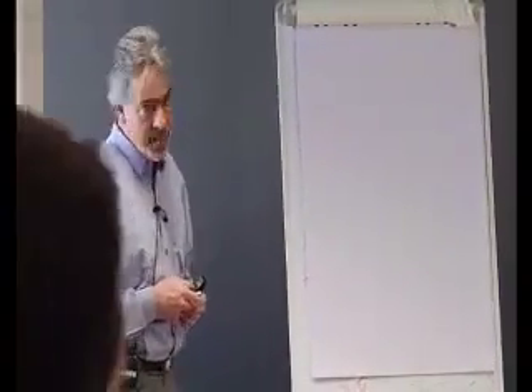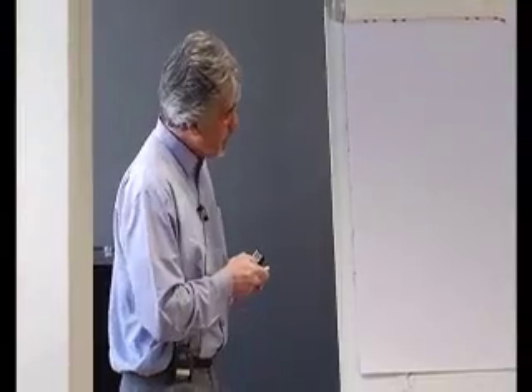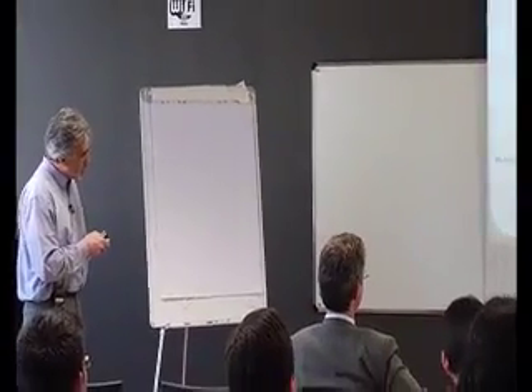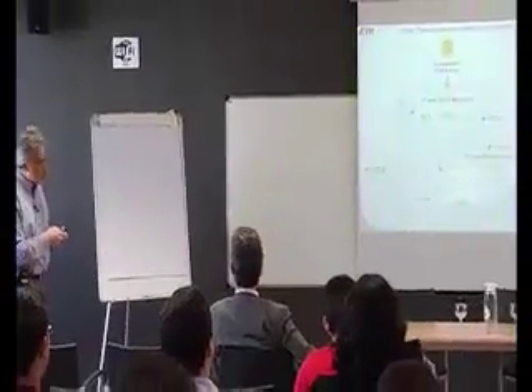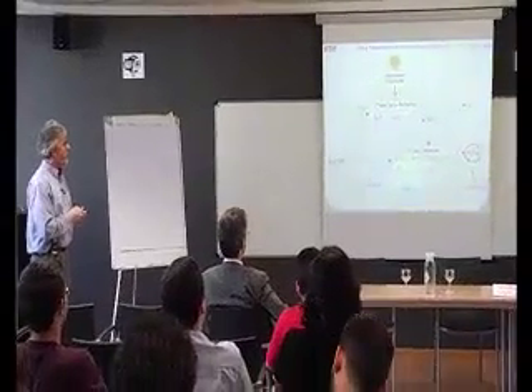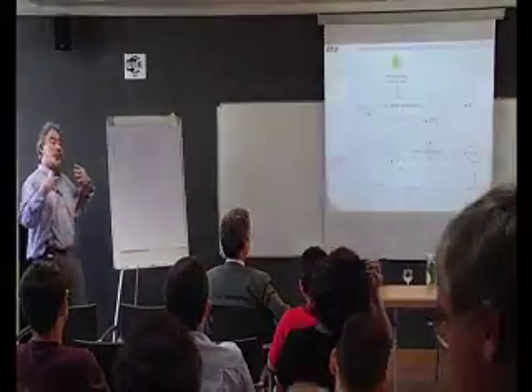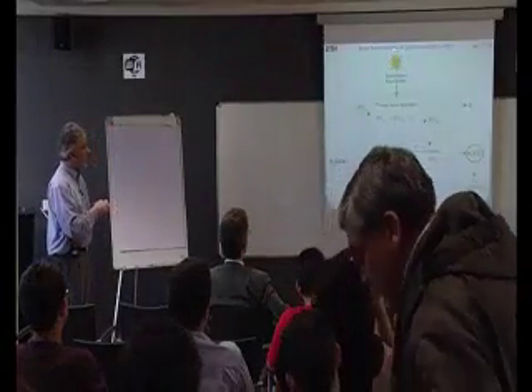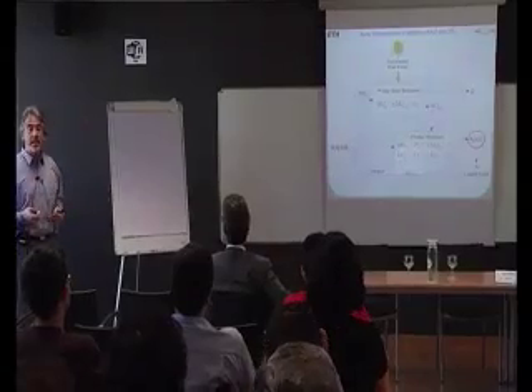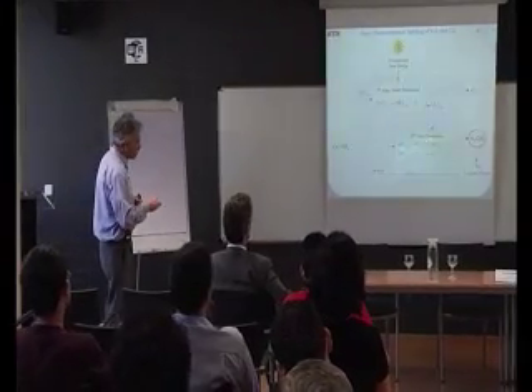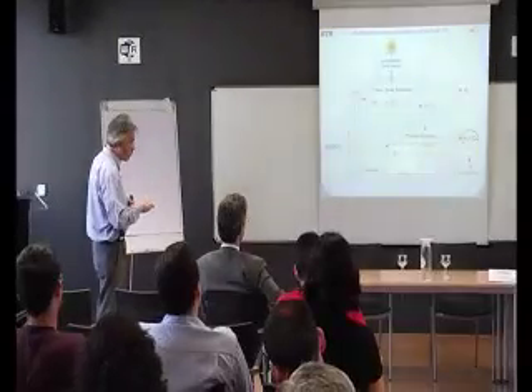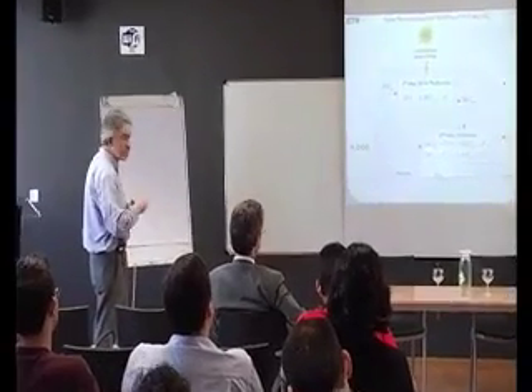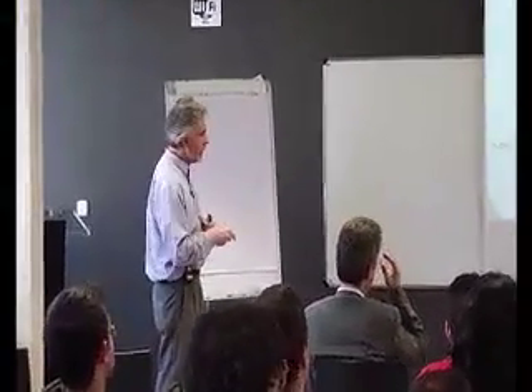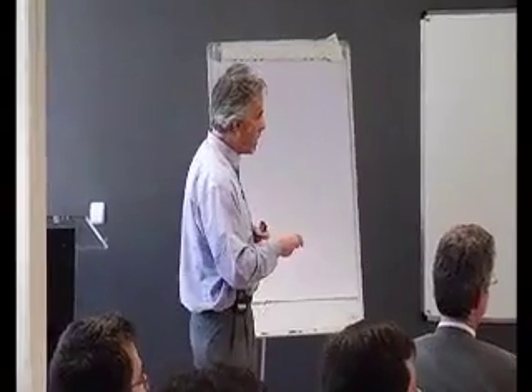And I'm going to be focusing on a two-step thermochemical cycle, and here is the diagram of this cycle. In the first step, a metal oxide, which is denoted by MOX, is thermally reduced and oxygen is set free. This is a highly endothermic step that proceeds at high temperatures, and concentrated solar energy is the source of this high temperature processing. In the second step, the metal oxide reacts either with water or CO2 to give hydrogen and CO, our syngas mixture. And the original metal oxide is reformed and recycled to the first step.